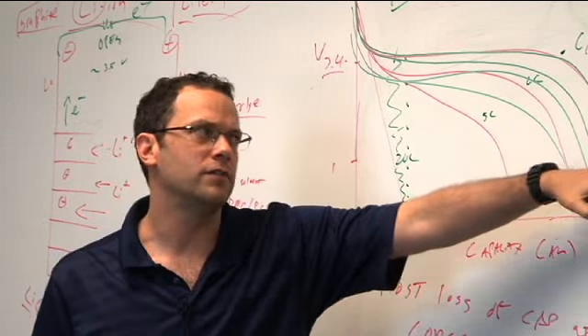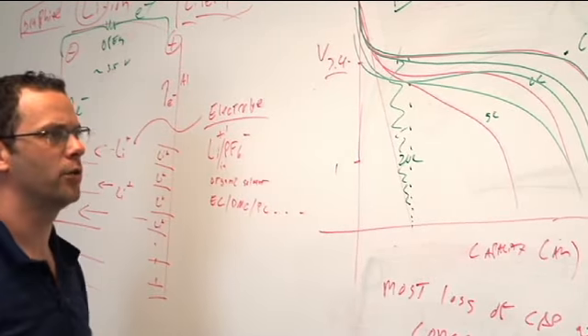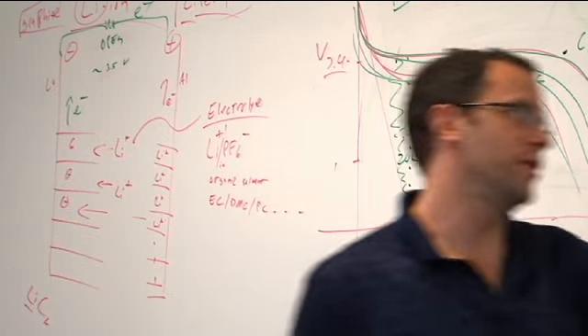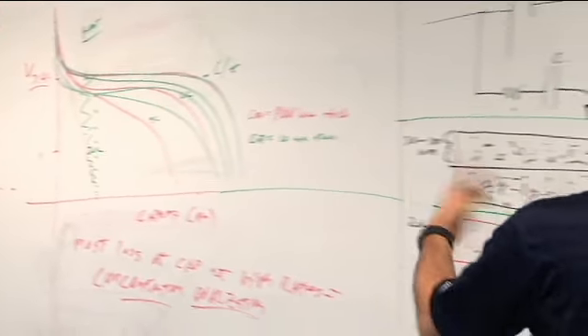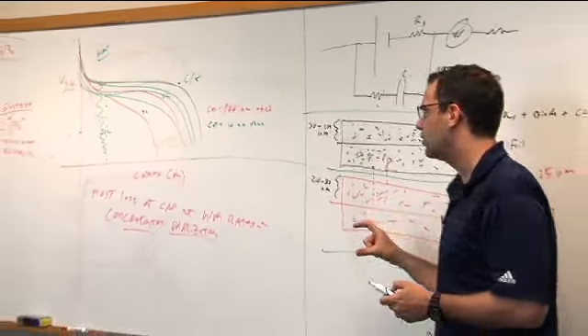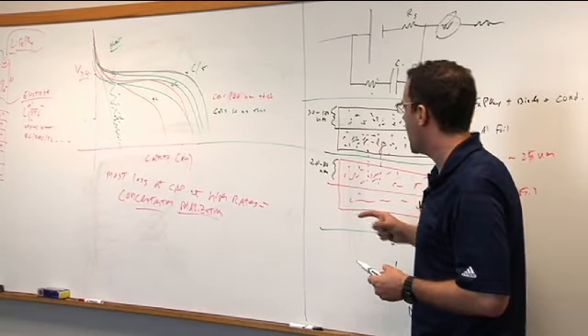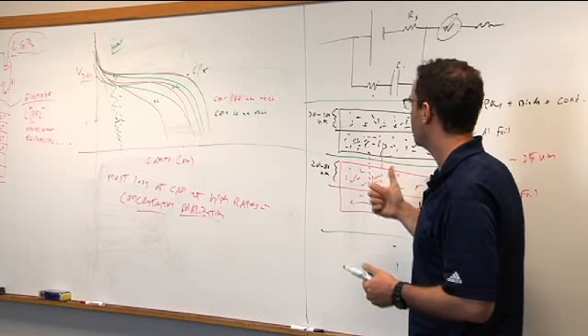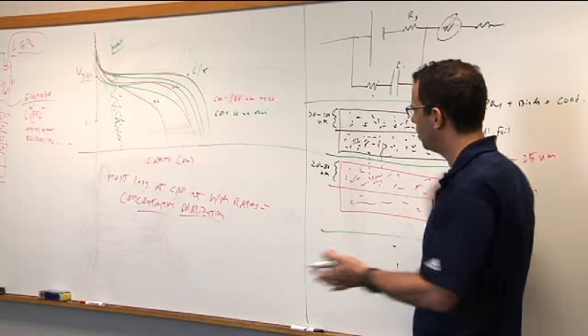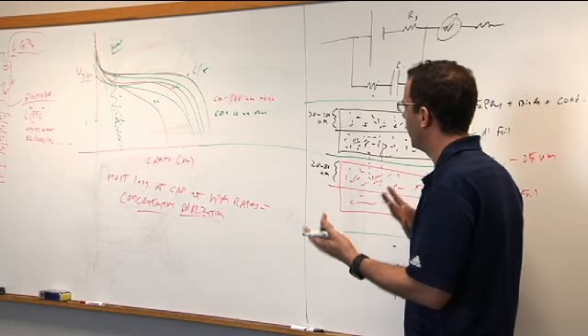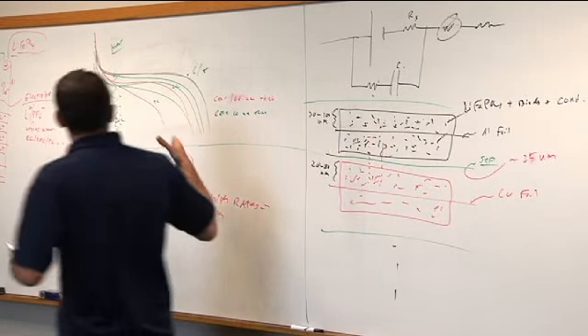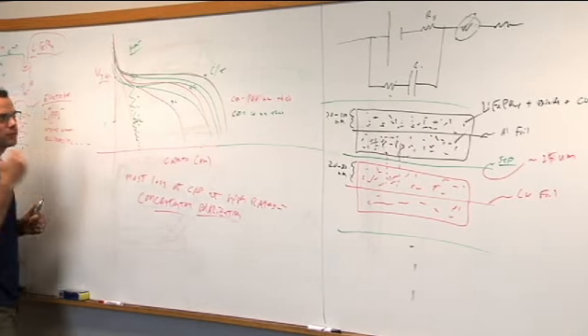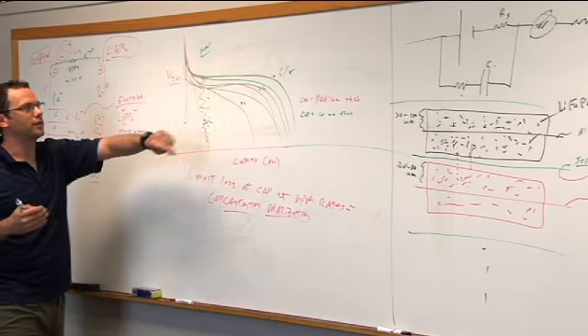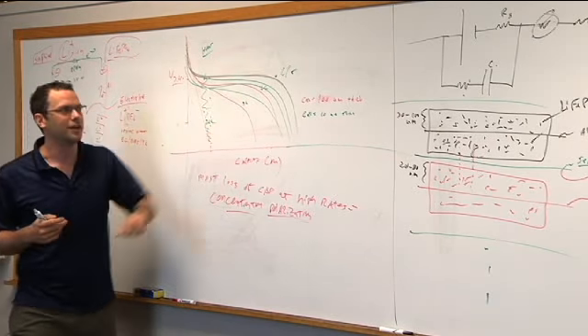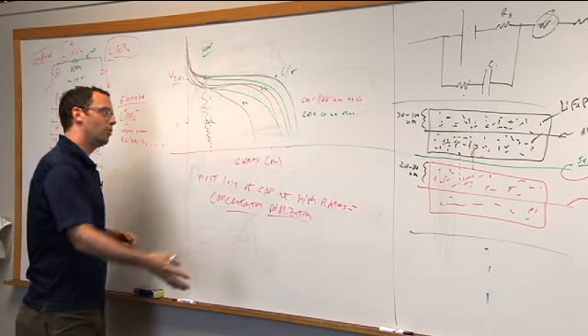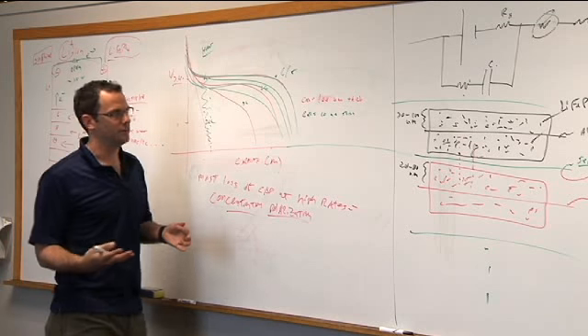When you talk about putting 10 or 15 or 20 micron thick cathode layers on these foils and then rolling them up and then putting them in the cans and backfilling with electrolyte, you end up with a battery that becomes almost entirely foil, separator, and can. There's almost no active material. So there's this huge trade-off where we want to have the most cost-effective, cost-efficient batteries that can withstand a reasonable rate, but we don't want to make the electrode so thin that it's prohibitively expensive.